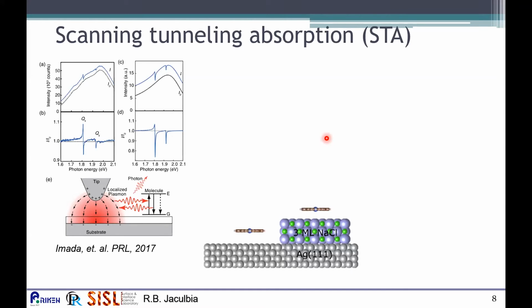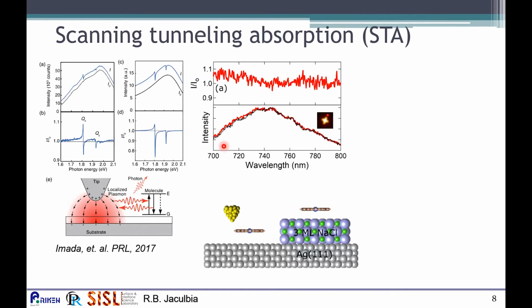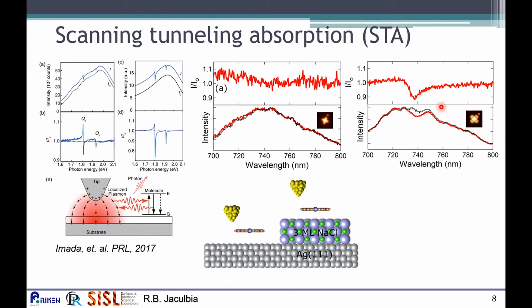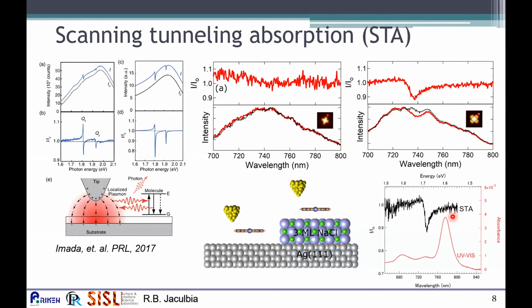First, when we look at the molecule on silver, we found that under the wavelength range used in our experiments, no absorption is observed. This suggests that resonance enhancement is not possible for the molecule on the silver 111 surface. Meanwhile, for the molecule on the sodium chloride, we observed a clear dip which corresponds to the absorption and the transition between the HOMO and LUMO of the molecule. And when we compare to room temperature absorbance measurements using UV-visible measurements, the absorption peaks are quite matched.